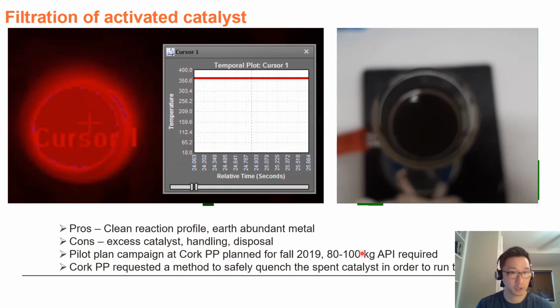Well, you don't want that much catalyst reaching temperatures in excess of 350 degrees in just a few seconds. And thus the Cork pilot plant requested that we come up with a way to effectively deactivate the Raney cobalt so that it was safe to handle even when dry. So in other words, we couldn't just drum up the stuff underwater, we actually had to deactivate it.